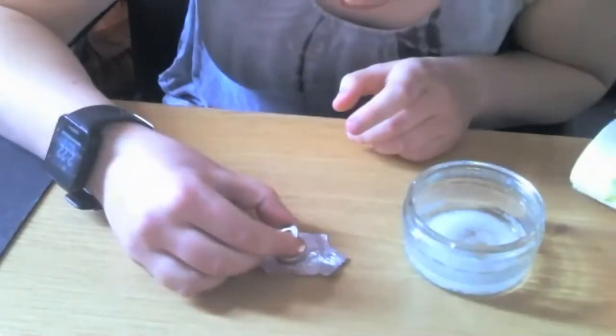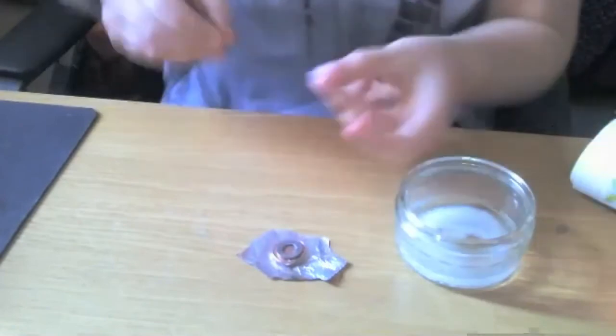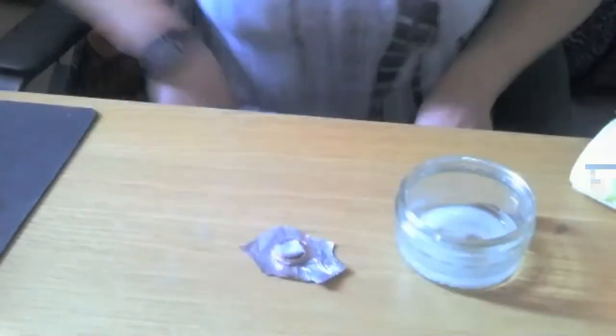Another thing to note: I'm using rather shiny coins which have been cleaned in vinegar beforehand. The reason is that if they're nice and shiny and clean without an oxide layer on top, they've got a better chance of producing better current. I'm going to do this a few times in a row — stacking the pile. There is nothing between each of the individual cell units, just contact between zinc and copper.